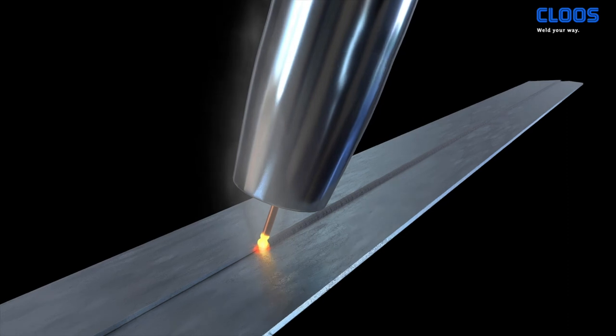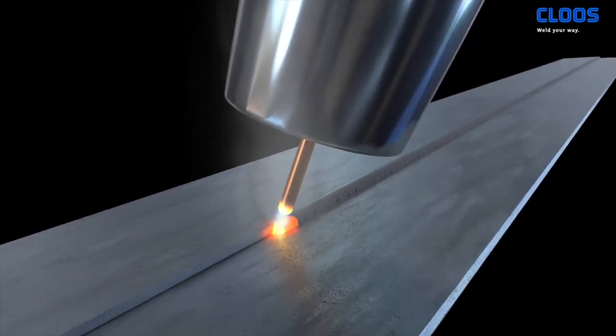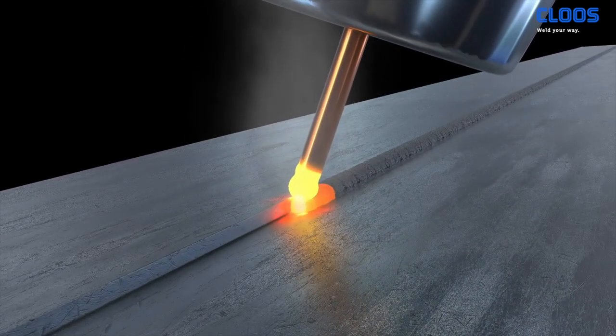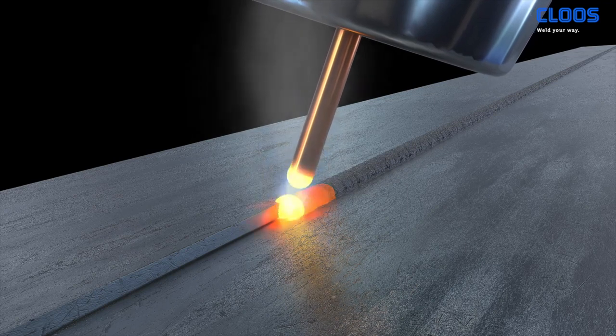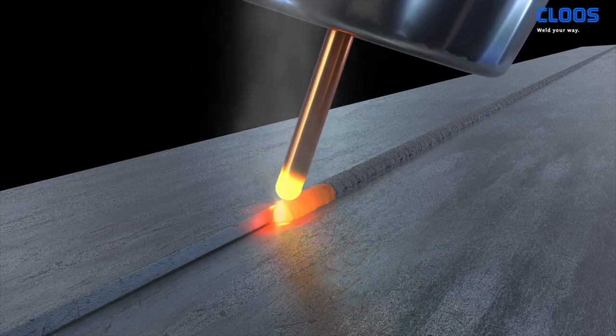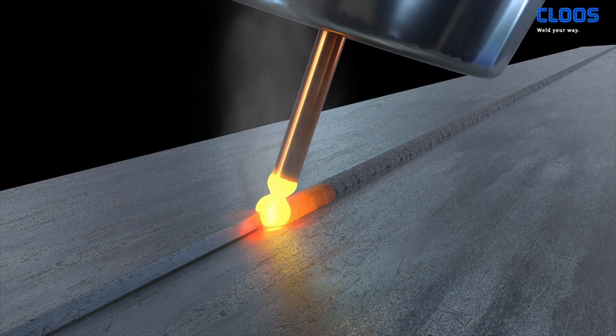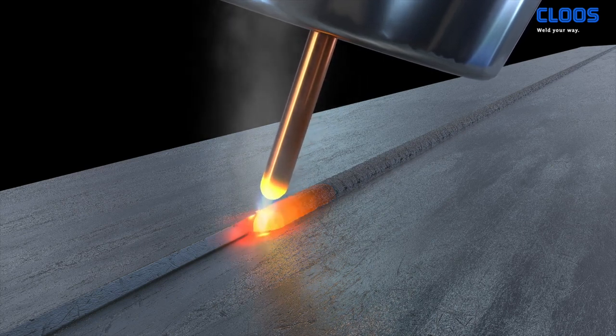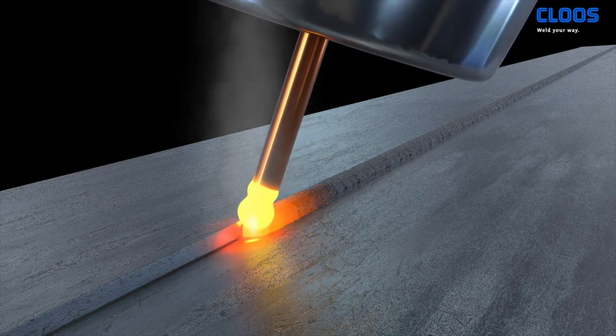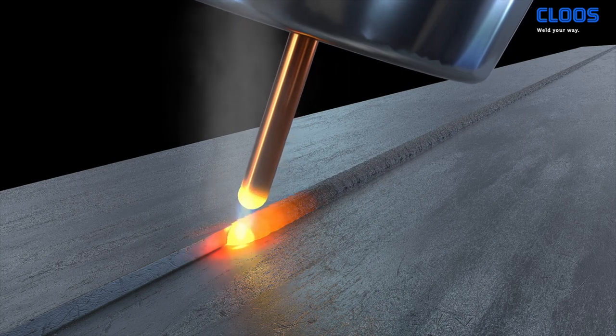With fine wire, the lowest possible current flows in an arc phase before a drop short circuit occurs. When the liquid wire end comes into contact with the molten pool, a molten bridge should form as free as possible. For this purpose, the current is reduced even further for a short time.